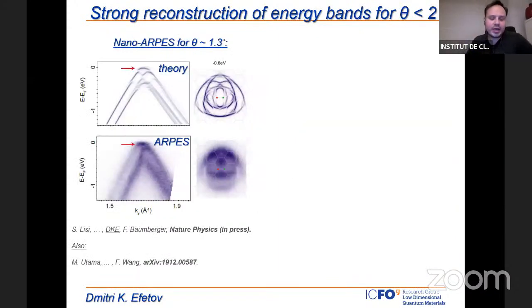Okay, and as I mentioned, what happens now with the band structure? Here we have calculated the band structure for a 1.3 degree device. And as you can see, if we look at the band structure now, it still resembles the band structure of AB stacked bilayer graphene. So we still get those two bands, which you can guess would develop hyperbolically.